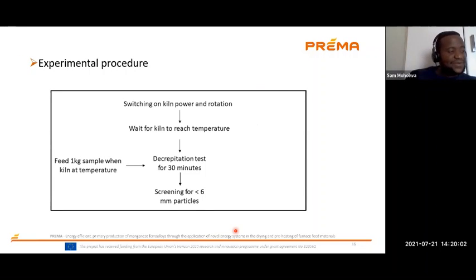Here, this is the experimental procedure. Firstly, we switch on the kiln power and the rotation, and we put in the set point temperature. Depending on the test, maybe 600, 800, and 1,000, as we have seen in the experimental plan. And this kiln was allowed to heat so that it can reach the temperature that was inserted into the controller, which may either be 600, 800, or 1,000. After the kiln has reached the desired temperature, 1 kg of the manganese ore was fed into the kiln.